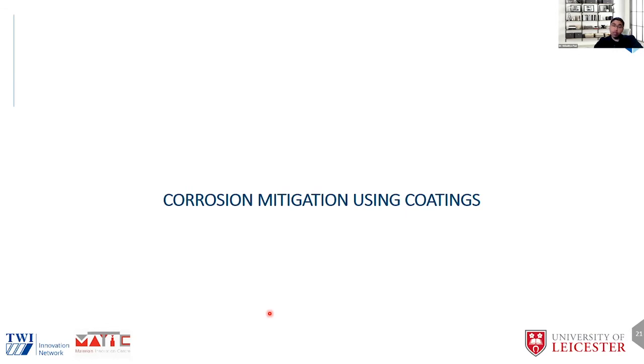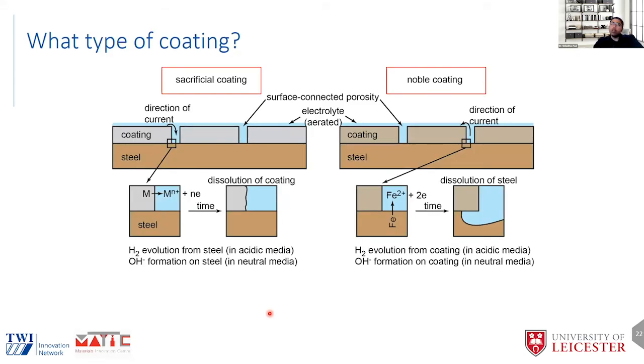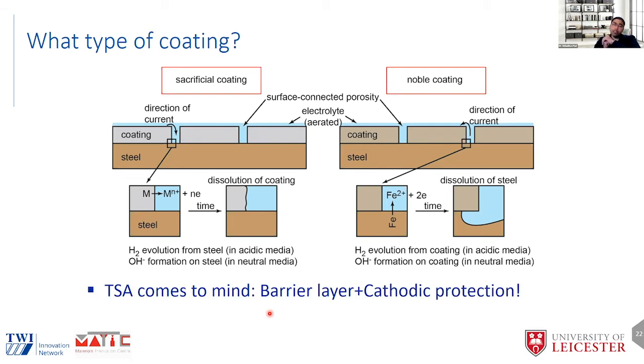Now I'm going to talk a little bit about corrosion mitigation using coatings. There are a couple of philosophies that people generally talk about when they are looking at thermal sprayed systems. One is the use of sacrificial coatings, where if there is a defect in the coating, you still get protection of the substrate because the coating itself is preferentially corroded, which is the case for aluminium, zinc, and similar systems. And if you want to have a noble coating, things like nickel-based systems on steel, then if there is a defect in the coating, your substrate would become the anode and get preferentially corroded. So that is one of the things that we were thinking about when we looked at various coating systems.